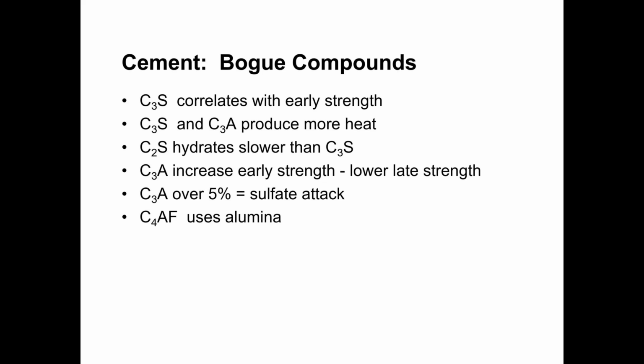And then C4AF doesn't really do a whole lot with regard to the strength. What it does do is it uses up any excess alumina. The A in C3A is alumina. So if we have a high C3A content, but we also have a high C4AF content, then the C4AF will help to offset the C3A as far as mitigating that potential for sulfate attack.